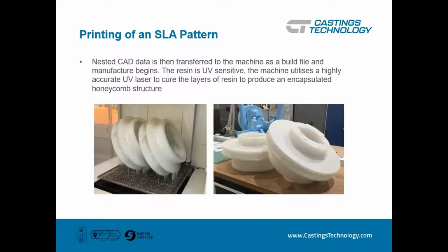So what we actually create here, although it looks solid, inside is a honeycomb pattern. That reduces the amount of resin that we use. It also, when that's exposed to 1,000 Celsius, tends to crumple in on itself. There's lots and lots of trapped oxygen, and it helps to burn it out. We don't want any ash or waste left in there. And that allows us to create a real good replica of the part with a little bit of contraction allowance on it. So that is our go-to process for low volume, high integrity Class A impellers. It's a very expensive process, by the way, but very, very good at what it does.